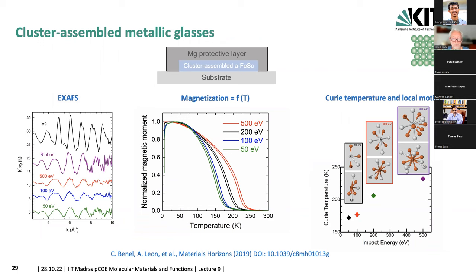So this is summarized here again, the magnetic moment versus temperature curve. So you see nicely the shift of the TC, and on the right side, you see the combination of the local motifs, the structural building blocks of the glass, versus the Curie temperature. So it allows us to form a new glass structure, and we have control over the formation of that by changing the size of the particle, changing the impact energy, and so on. So that is nice, that we have a means of changing the size.